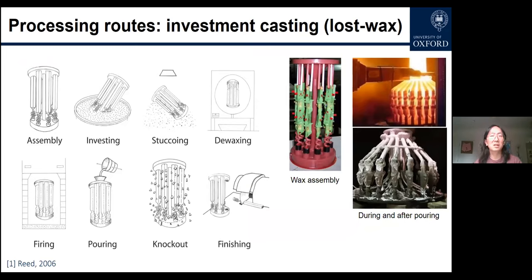For making turbine blades, one of the important developments is something called investment casting, which is as simple as it shows. In the beginning, you have a wax pattern assembly, and you dip it into slurry, you invest it, and then you coat it with bigger, coarser ceramics, and you do this process many, many times until you have a big shell. You fire it to de-wax it, make it harder, and the wax is going to be lost from the bottom. So that is also called the lost wax process. Once you have the ceramic mold, you can pour your materials into the cavities, and then they can be solidified in this way to make your material.